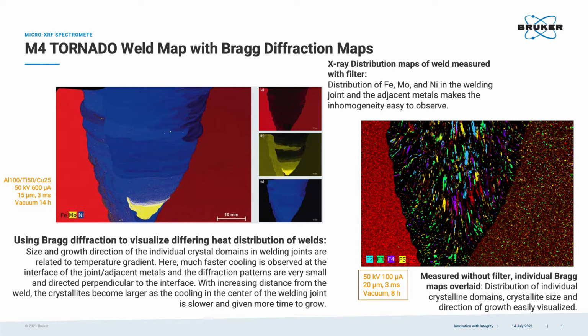And the other problem with these welded things is the Bragg diffraction can be a bit misleading in a way, because the grain structure of steels, the orientation you get depends on the phase that's there. You can get different types of steels with different grain contrasts. We like to do that with EBSD. But you're right, it does look great.